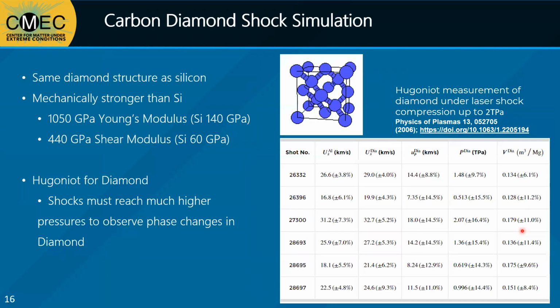Our next material of interest was diamond carbon. Diamond shares its base diamond cubic crystalline structure with silicon, but it is much stronger. It has a Young's modulus of 1050 gigapascals and a shear modulus of 440 gigapascals, almost 8 times that of silicon. In the Hugoniot data for experimental shots on diamond, we see that piston velocities above 10 kilometers per second are used, with resulting pressures in the terapascal range. The shocks for diamond need to be much higher to reach pressures to observe any phase changes in diamond.